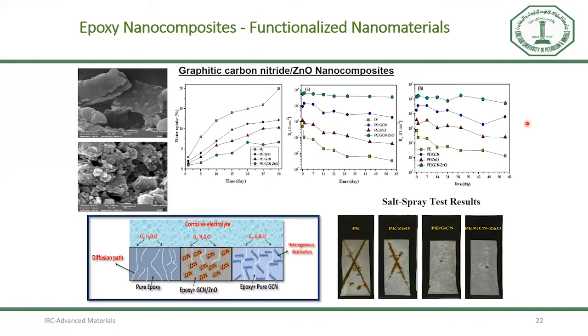Then, to replace the zinc-rich primers in the field, we used graphite carbon nitride zinc oxide nanocomposites in the epoxy coatings. Finally, we found that water uptake is reduced when we incorporate this nanocomposite into the epoxy coating, because it can lengthen the pathways of aggressive ions from the electrolyte towards the material surface.